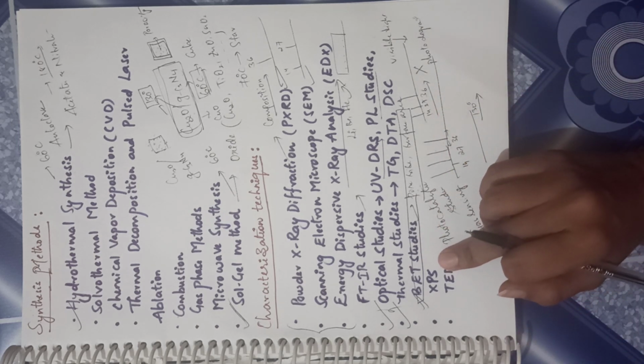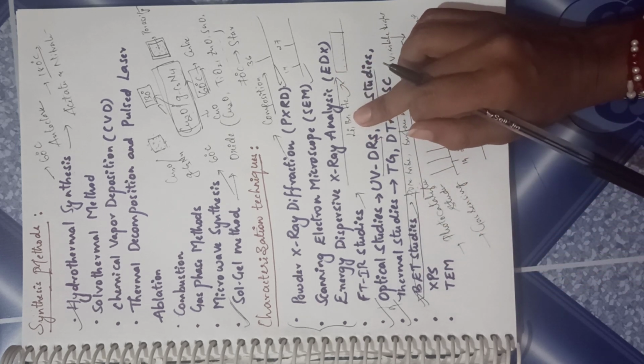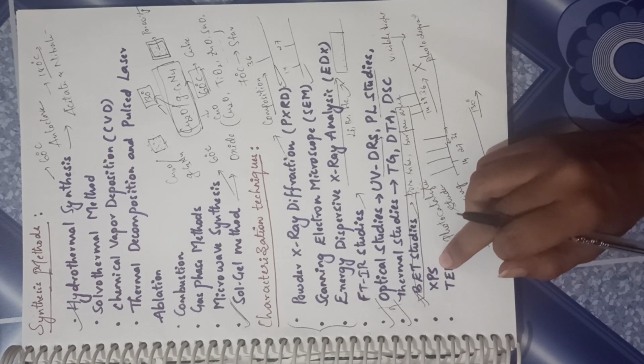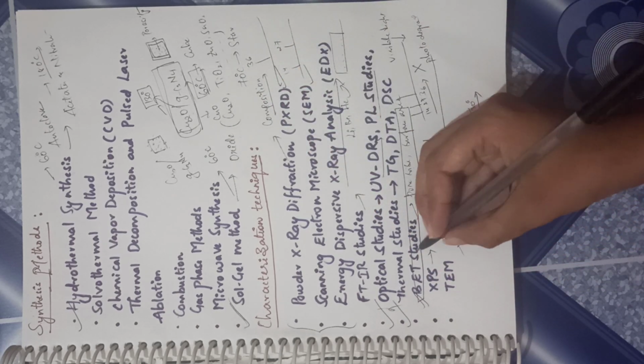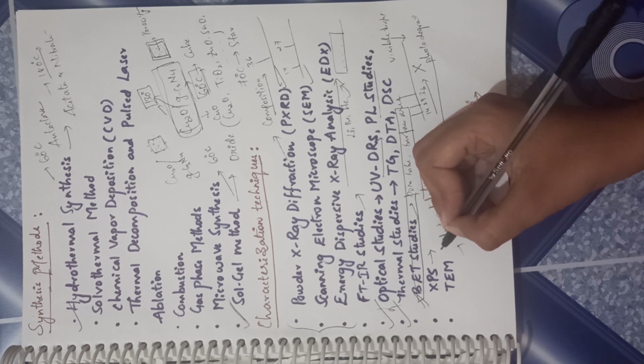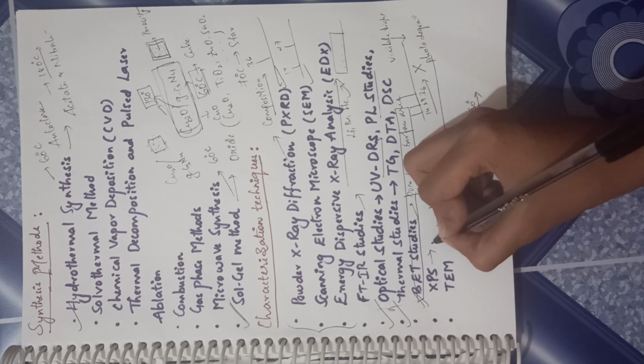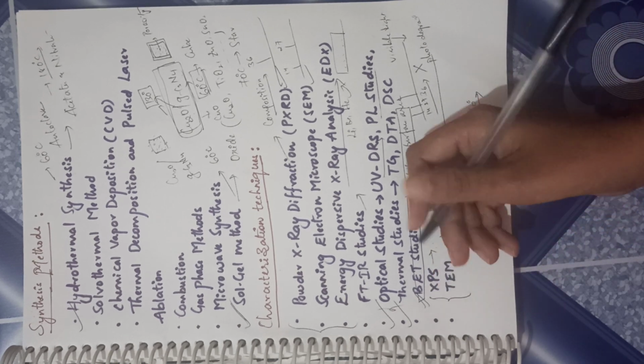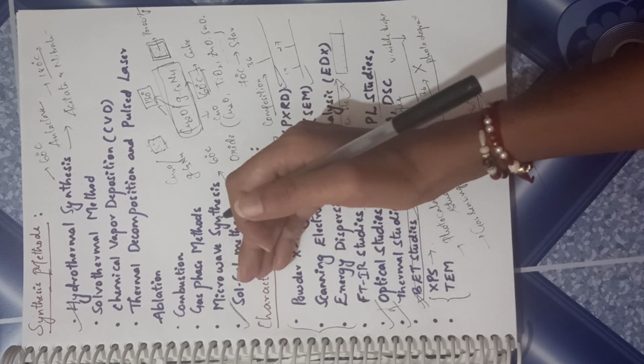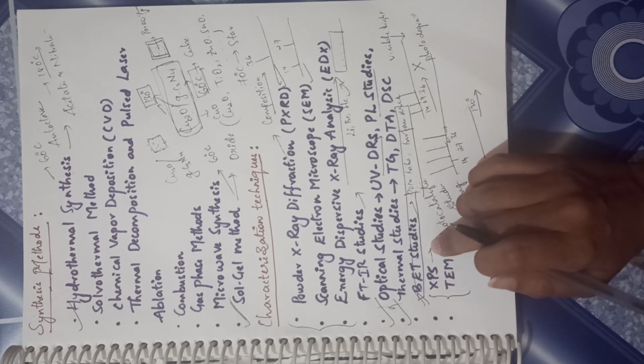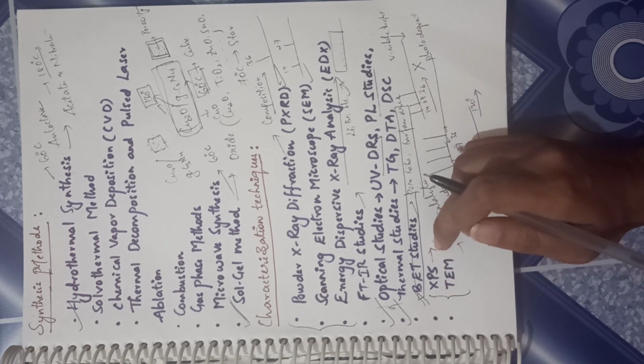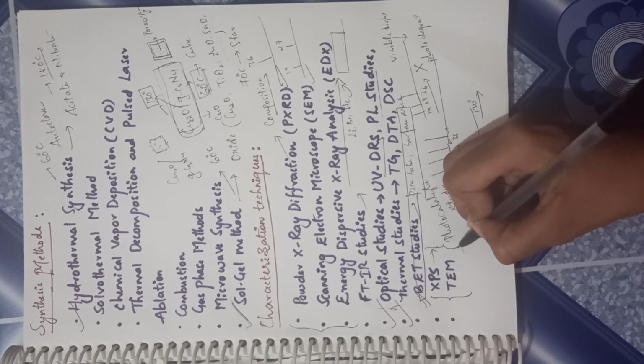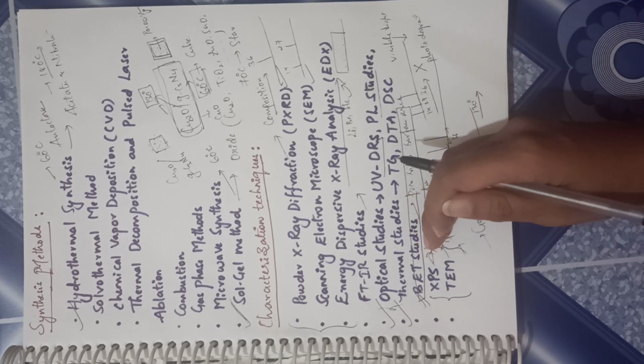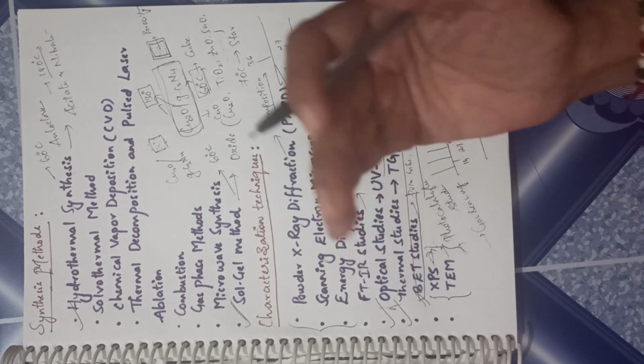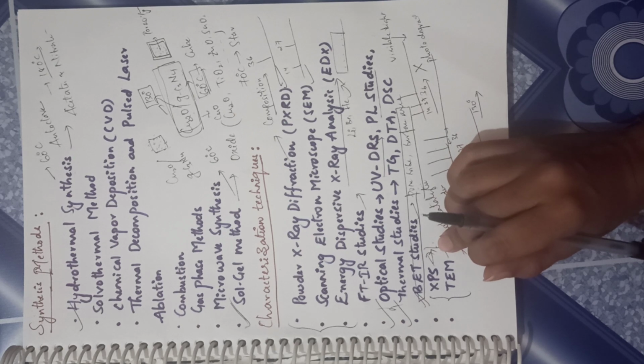Now XPS. I have told here that EDAX cannot detect elements like lithium, helium, beryllium. Now this can be detected using XPS. XPS is also used to confirm the composition, and the various oxidation states present in the sample can be confirmed using XPS. Now these two characterization techniques are always preferred to be done in the last, once you are done with all these techniques, because XPS provides a lot of data. So if you do XPS for 6 to 7 samples and later sit and try to analyze it, you will get confused totally. So my guide always asks me to do XPS and TEM once you confirm all the characterizations, once you do even your application part, and then we have to do the XPS technique,